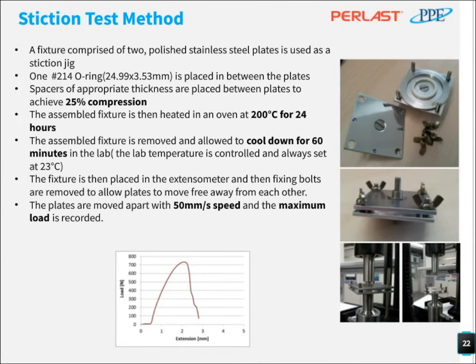Now I'm going to show how we tested the stickiness of our material and some competitor materials. Okay, in this test, we have two pieces of polished stainless steel plates, and we place the O-ring in between them and compress by 25% using some spacers. And then we fix the compression by using bolts, and we place the whole jig in compressed state in an oven, 200 degrees Celsius for 24 hours.